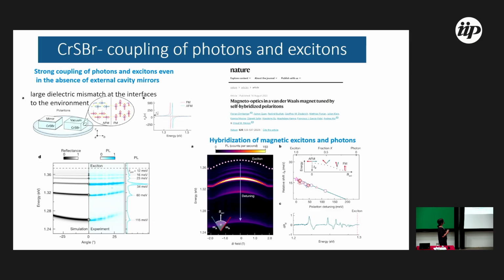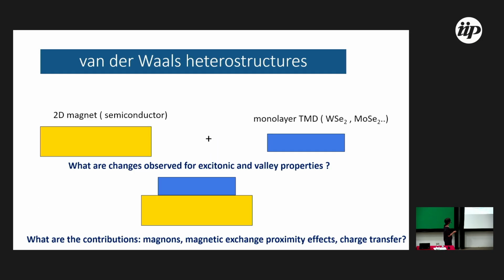And it's also interesting, this material, because you don't even need a cavity. As there is this large dielectric mismatch between the material and the interface, you can have polaritons, that is excitons coupled with light. And these polaritons are sensitive, coupled with magnetic properties as well. You can measure polaritons and show this phase transition just by looking at polaritons in this material. So it's a very interesting system to investigate polaritons.